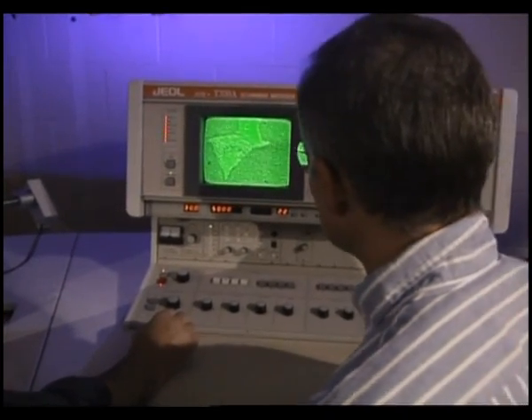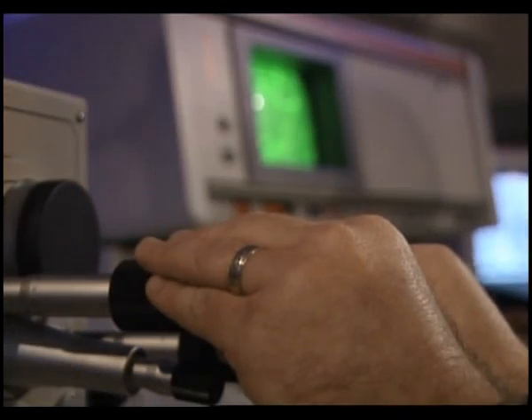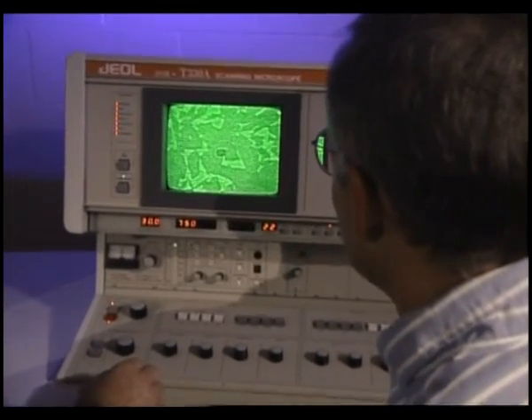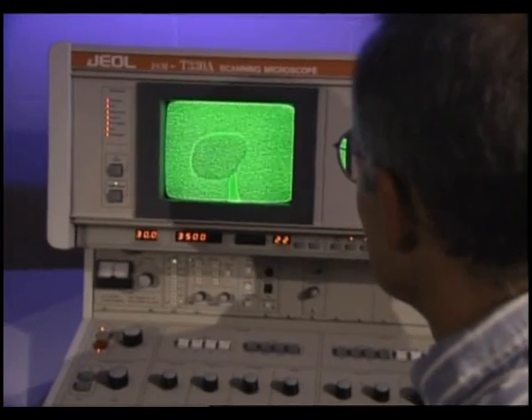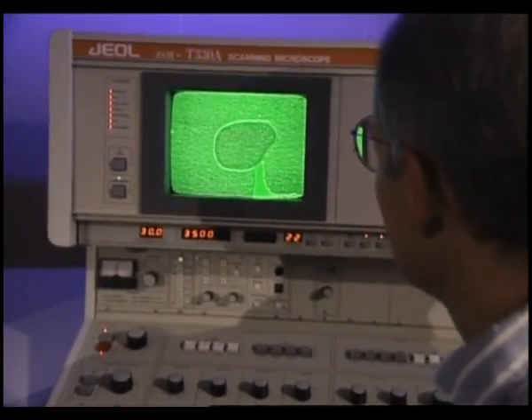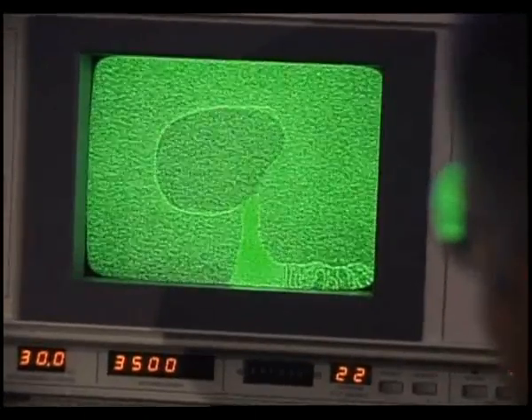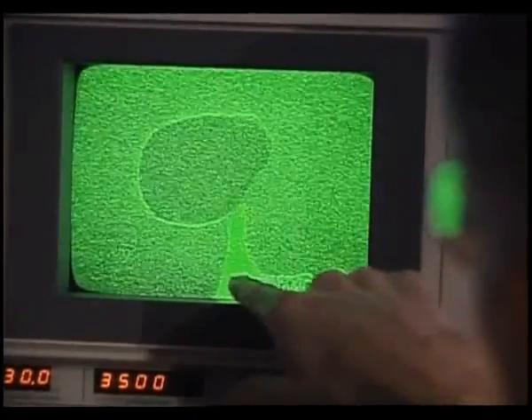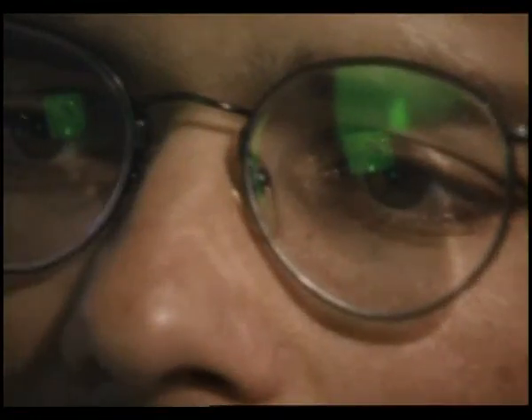Pearlite, lots of inclusions. Let's focus it real fast, and then go back down in magnification, see what we have. They are looking for potential weaknesses and defects in the steel. Higher magnification shot. Lots of ferrite and pearlite, big inclusion. That's a big one, probably a big old manganese sulfide. That's a big one. Big manganese sulfide. As they suspected, the steel is full of large manganese sulfide inclusions, chemical imperfections that create weak areas which cause the steel to be brittle.